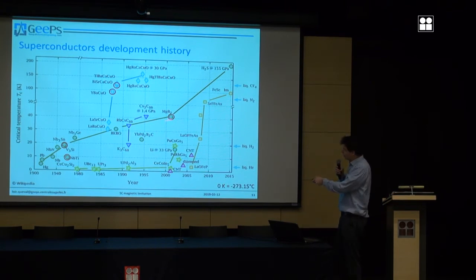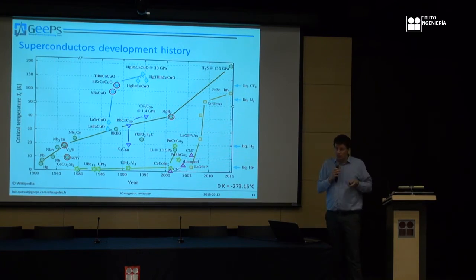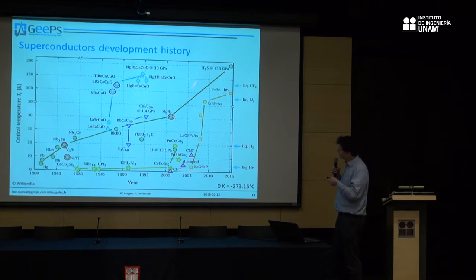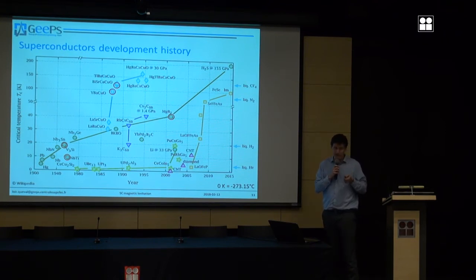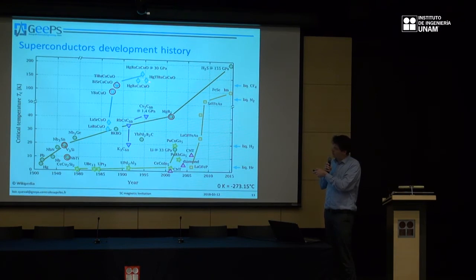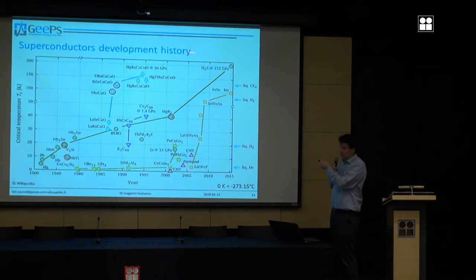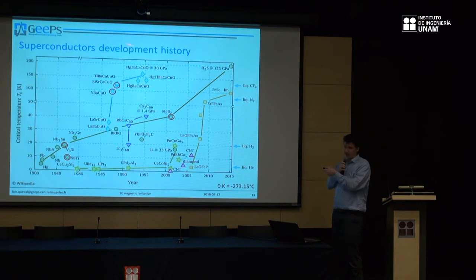And the goal is to go as high as possible, if we can, to room temperature, so that we don't need any more cooling, okay? As of today, the highest TC that we found, at ambient pressure, is 138 Kelvin. And if you put pressure on the superconductor, you can go a little bit higher, or even higher. This one was discovered, I think, last year or 2 years ago: hydrogen sulfide, but you need 155 gigapascal.